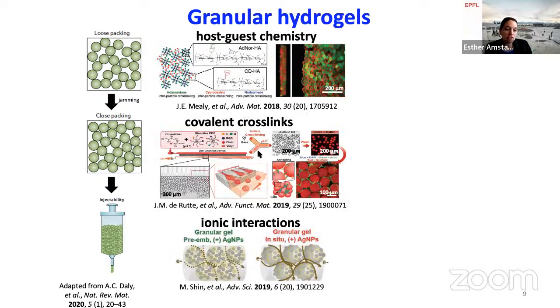Now, the problem is that if you 3D print these kinds of microparticles into granular materials, they often retain their shape, but they're extremely weak because the particles are very weakly connected to each other, mainly through physical van der Waals interactions. This weakness has been recognized by the community, and a lot of different strategies to link different microgels together have been introduced, including host-guest chemistries, covalent cross-linking through their surfaces, or through ionic interactions.